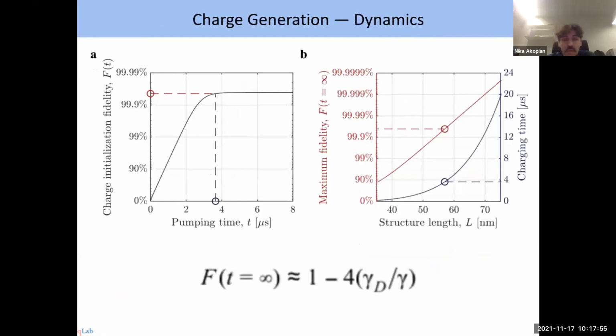Of course, we simulate the result, and this is our pumping time, and this is a charge initialization fidelity. And we can see that we can reach again way above 99% of creating charges in our system if we wait a few microseconds. Clearly, the more we wait, the more sure we are, but at some point it saturates. This is a simulation of a realistic system that we can grow, and we can see that after 4 microseconds we are essentially able to